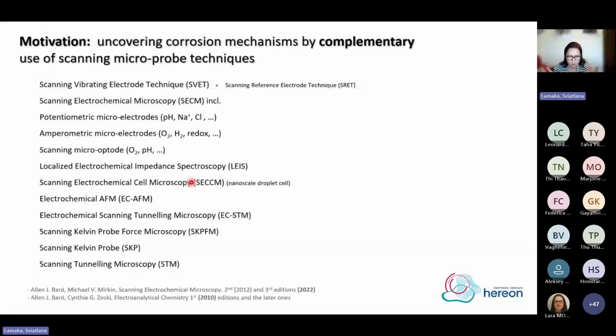It is also very important to understand that all the electrochemical and corrosion processes happen at the metal surface, at the interface, rather than in the bulk electrolyte. That's why there is a big difference in the concentration of species between the bulk electrolyte and the metal surface. Here I have an example of approach curves, from 1 millimeter to the metal surface. In this case, it's a platinum 270 micrometer disc embedded in epoxy. We injected either negative or positive current, observing the oxygen reduction reaction with alkalinization in this case, or the oxygen evolution process with water oxidation in the case of positive polarization. You see that as we approach from 1 millimeter height to the surface, we see significant changes of local pH. I will later on speak about the microprobes that we used for this.